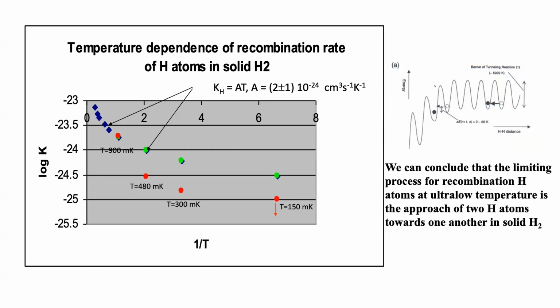We understand that what we are measuring, and from this recombination rate we determine the diffusion rate, is not characterizing the fastest movement of hydrogen. It characterizes the slowest movement, when atoms move toward each other and the process is very slow.